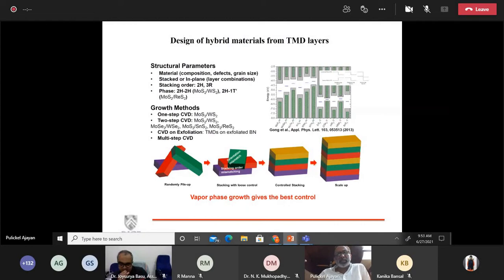Another fascinating aspect of these type of materials is the fact that, as I mentioned in the beginning, you can mix and match and build up these stacked structures just like a deck of cards. And this is really very interesting because you can make artificially stacked materials that have not been shown before. So I can think about, let's say, taking a graphene layer and a boron nitride layer, which are almost isostructural but very different electronically, and then stacking them together and seeing what these hybrid materials can provide in terms of properties.